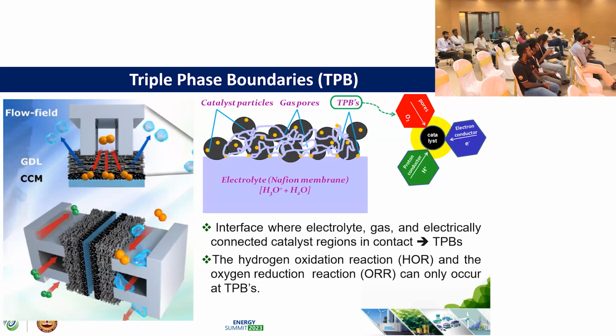So what are these triple phase boundaries? These are the interfaces where the electrolyte, gas, and the electrically connected catalyst agents should be in contact. This kind of active site should be increased instead of just increasing the surface area. This is applicable to both the anode side and the cathode side, where the hydrogen oxidation or oxygen reduction reaction will be occurring. So we have to understand that we have to improve the triple phase boundaries.